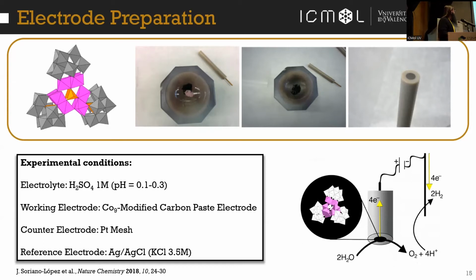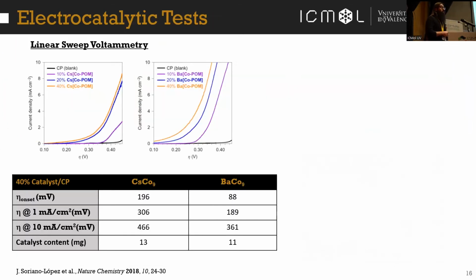The first thing we did was a linear sweep voltammetry. In a linear sweep voltammetry, we increase the potential and we measure the current intensity we obtain. So here, as we increase the potential, we see an increase in the values of the intensity. And that means we have a multi-electronic process. In this case, it's a catalytic process, which is water oxidation for us.